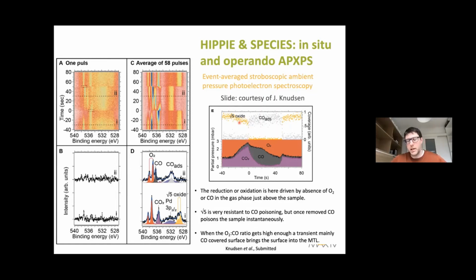In this particular case, with the oxygen-rich phase, you have a native oxide that is very inert in its interaction with CO, but once you consume it and create metallic palladium, it very quickly becomes covered by CO and gets poisoned, so the reaction stops. So this is very good to know.